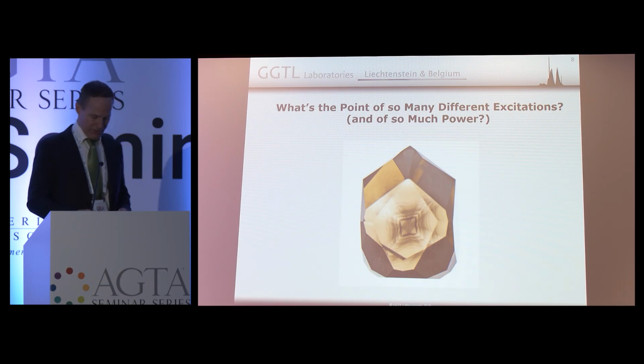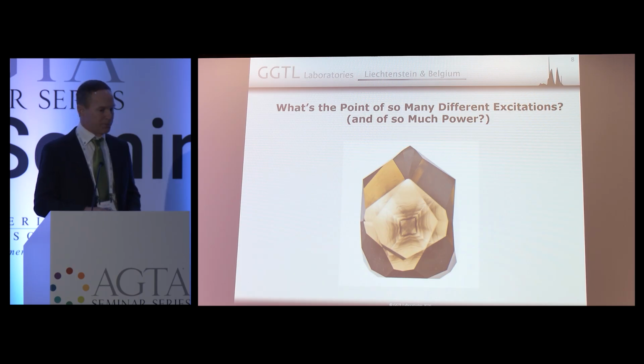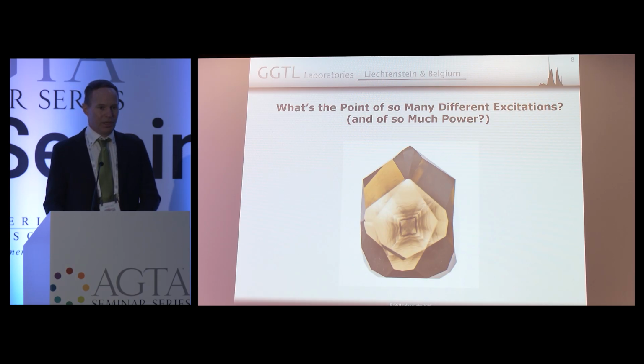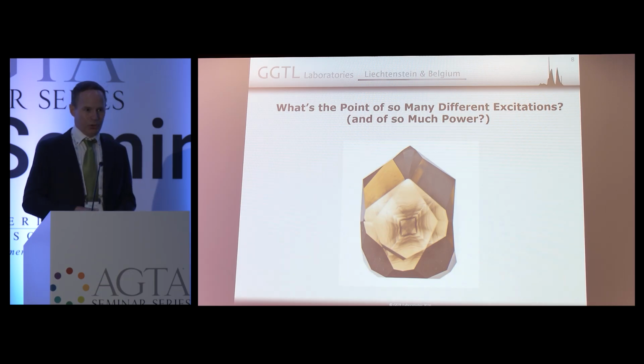This is an example that we had recently at the lab. This is a typical Zimbabwean stone with a beautiful phantom in the middle. This phantom shows that the diamond is predominantly of cuboid growth. Cuboid growth, being not cube. I always have to distinguish those two.